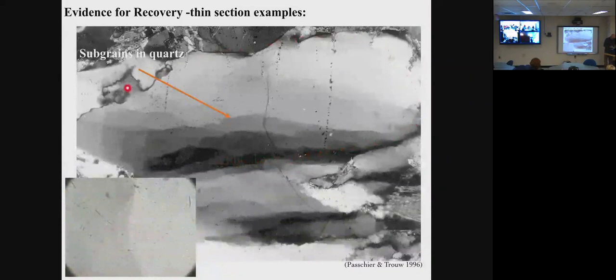Okay, this is a single grain right here, and the grain itself has zones of extinction. Fairly clear here, darker, darker, and then black. So the subgrain boundaries here are zones where we have a lot of pileup of dislocations. If we were to measure the optical axis of this crystal, I'm just going to schematically draw a line here, which would be, let's say, the orientation of the C-axis. In this zone here, it may be oriented like this, in this zone here, like this, and in this zone, like this. You'll notice that the angle is very, very small. Your eye will perceive these different gray zones as subgrain boundaries if the angle change between these optical axes is less than 15 degrees.